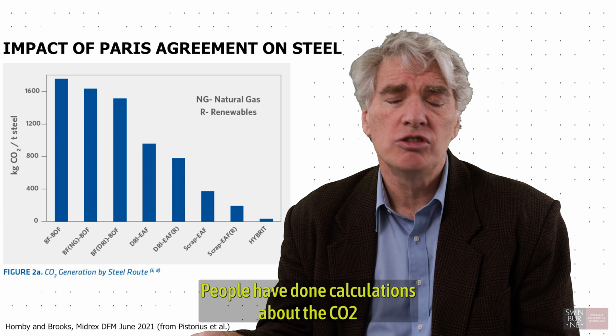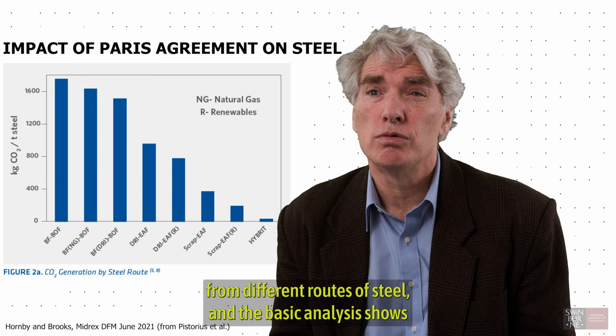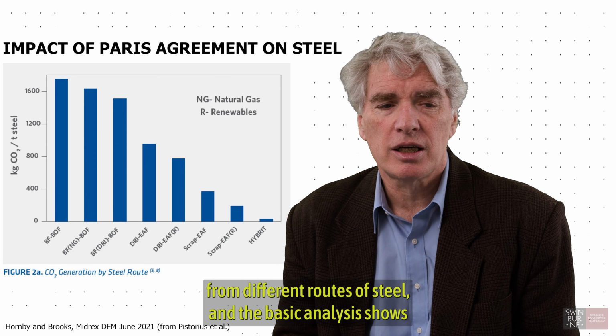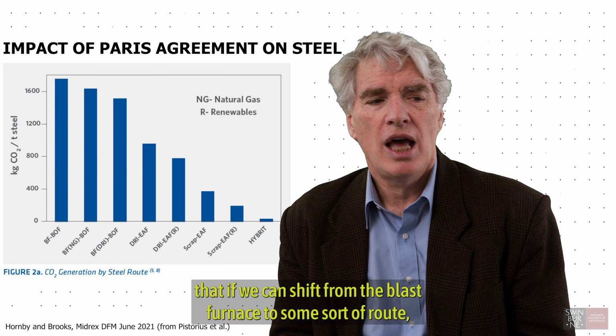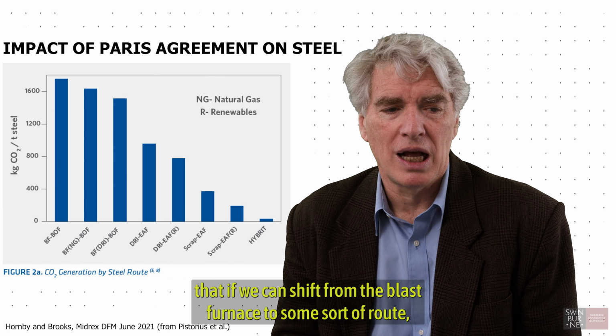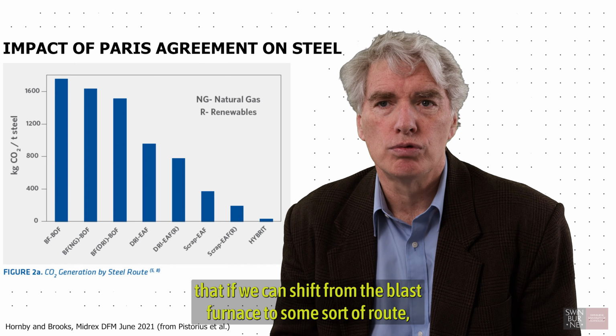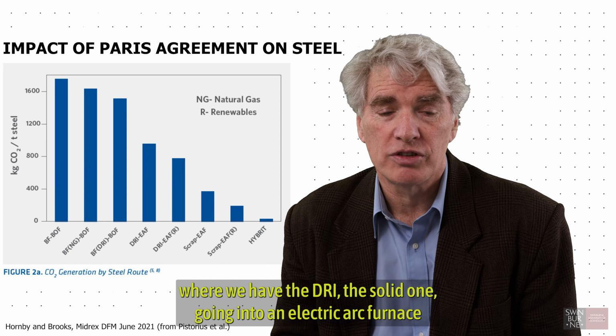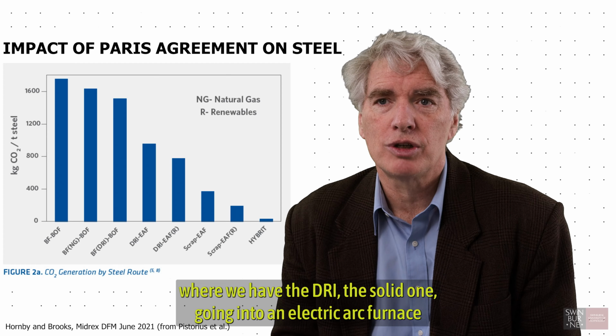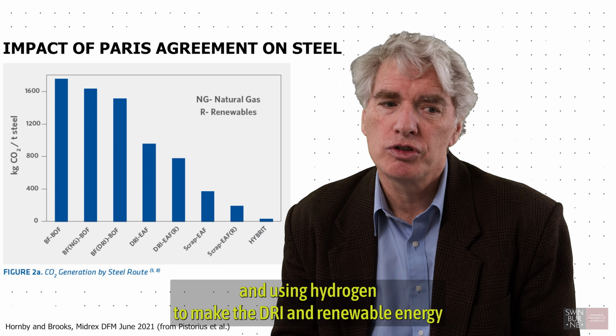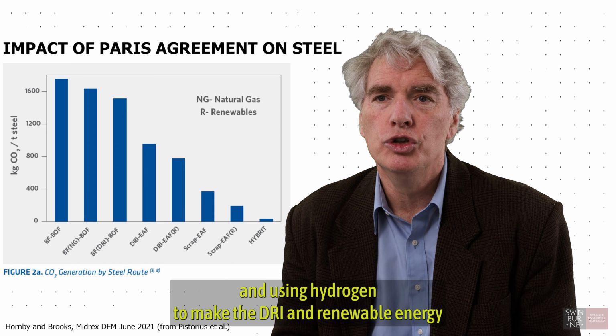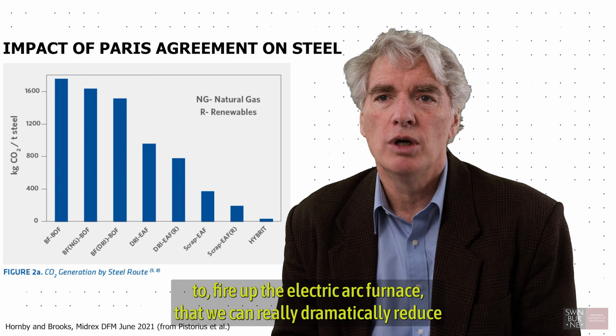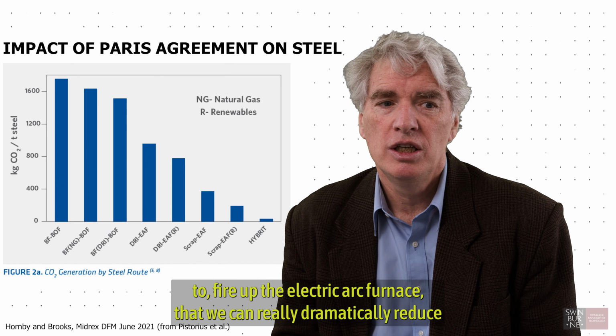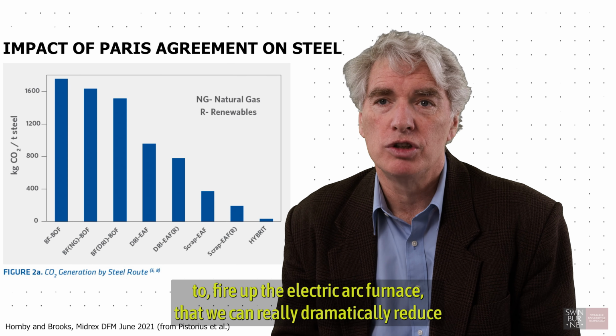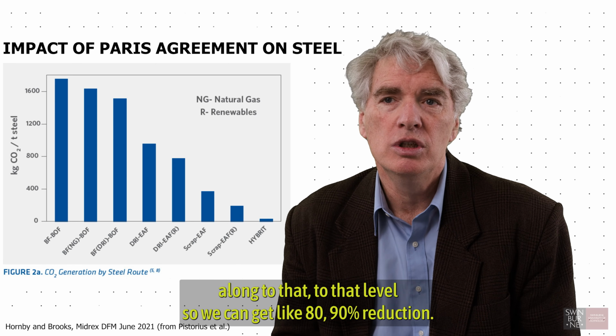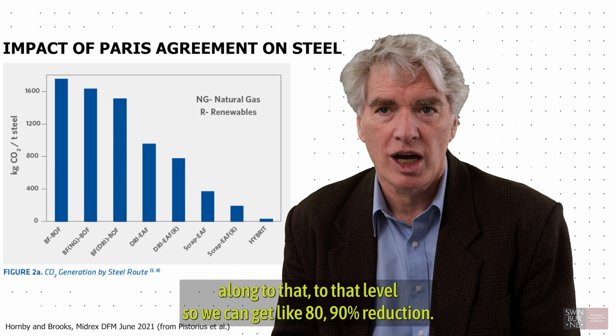People have done calculations about the CO2 from different routes of steel, and the basic analysis shows that if we can shift from the blast furnace to some sort of route where we have the DRI, the solid one, going into an electric arc furnace and using hydrogen to make the DRI and renewable energy to fire up the electric arc furnace, that we can really dramatically reduce along to that level. So we can get like 80-90% reduction.